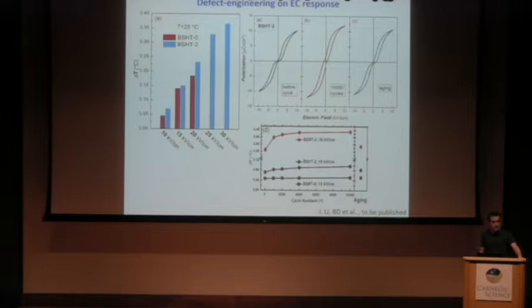And last question. I guess I'll just limit myself to a couple of points. Do you think with the aliovalent doping that when you apply the electric field, vacancies will start to move? And in the magnetic ferroelectric composite, do you think we need to include the work done on the barium titanate in your overall energy balance? So for the last one, yes, we have to include many things, actually. Because once again, we have a thin film, and what we did, actually, we considered just the caloric effect of the magnetic layer. Of course, the substrate is much bigger, and therefore it will impact the caloric property, and the interface also, because you have elasticity at that place. So you have to consider magnetocaloric, elastocaloric, and electrocaloric, plus the losses of all of them, of course. And the first one was, I forgot. For the defects moving? Yes, in this kind of case. Yes, exactly.